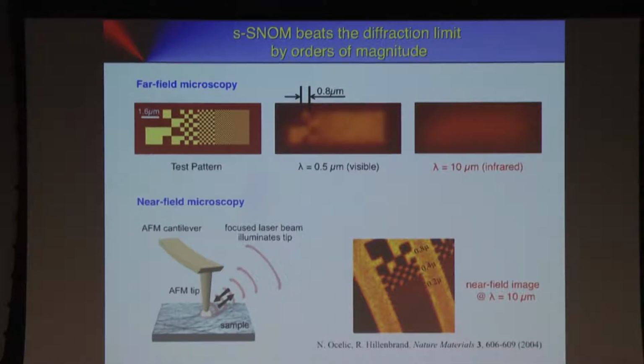So that's an early example that we did. We looked at a test pattern that was an implanted structure in silicon carbide. We looked at it with a visible microscope, so you see here some of the squares in the range of micrometers can be resolved. That's a far-field image at 10 micrometer, and you don't see anything because of the diffraction limit. Then we take this sample, put it in a microscope, and collect the light scattered at the AFM tip here, 10 micrometer wavelengths from a CO2 laser, and you can nicely see all the squares here down to 200, 100 nanometers. So it shows already this big difference between diffraction limited imaging and our kind of super resolved imaging based on near-field microscopy.